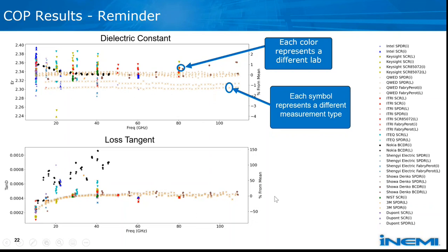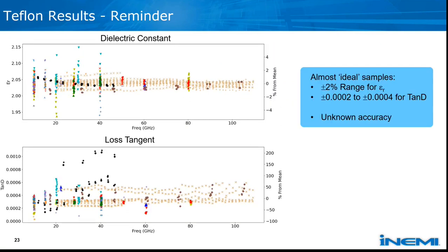So if you send your sample off to a lab to have the measurements done and you get back a result, this is kind of the error that for sure you at least have in your characterization. We don't have an ability to agree on a value between different labs that's better than, say, plus or minus 2%. If you go on to the next slide, we have similar results for the Teflon.